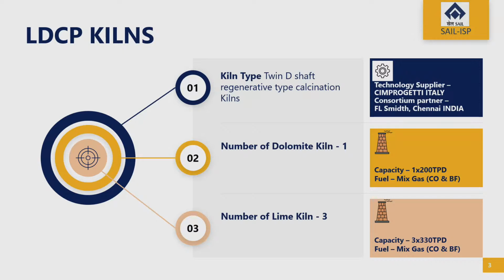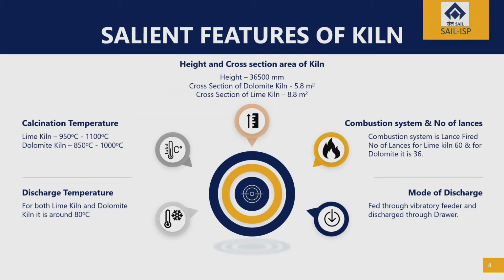In ISCO, we have four dual shaft kilns. Three are lime kilns, having a capacity of 330 tons per day, and one is a dolomite kiln, having a capacity of 200 tons per day. These are the basic parameters of our kiln. The temperature we maintain is around 950 to 1100 degrees centigrade for calcination. The combustion system we use is Lance Fired, and mixed gas is used for that purpose.